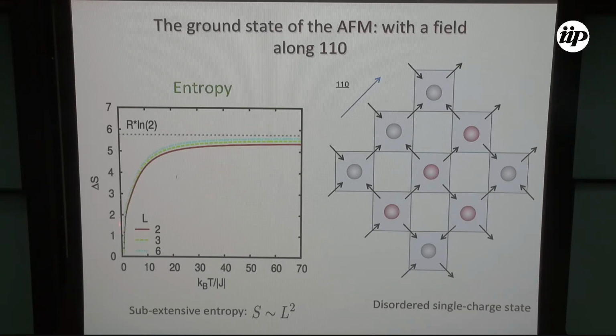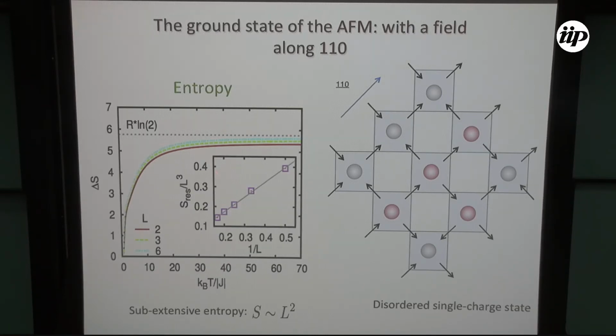You see that if you now look at the entropy, this is for Monte Carlo simulation. So if you look at the entropy as a function of temperature for different system sizes, you see that although at L equal 2 you don't reach, even at 70K, you don't reach R log 2. As you start increasing the system size, you can show that the entropy scales like L squared. So it's not giving you an extensive entropy, just a sub-extensive entropy.